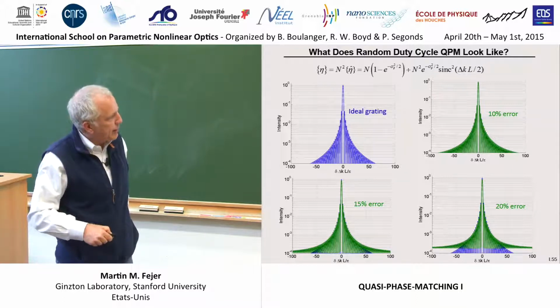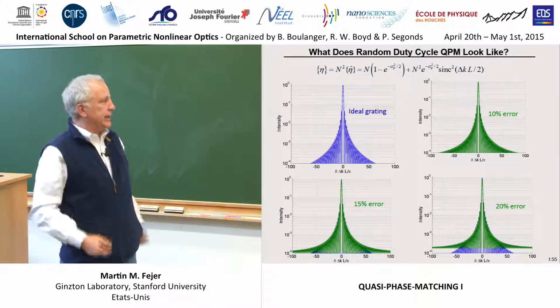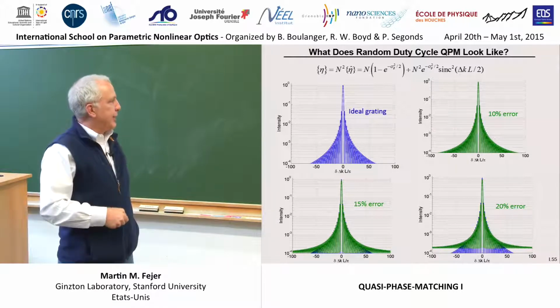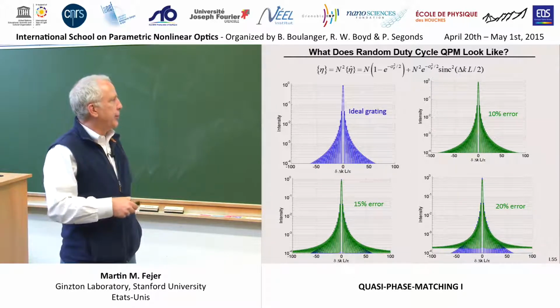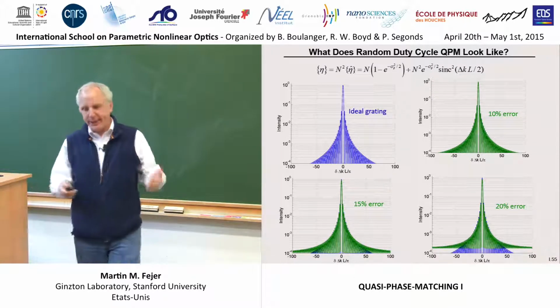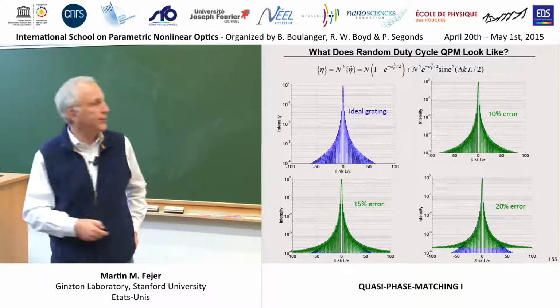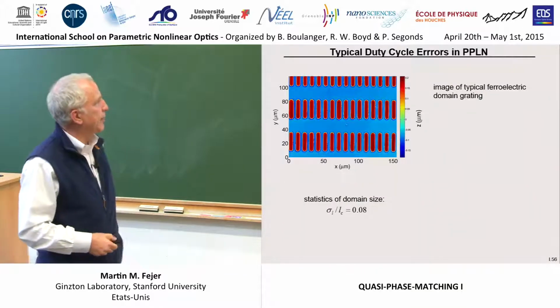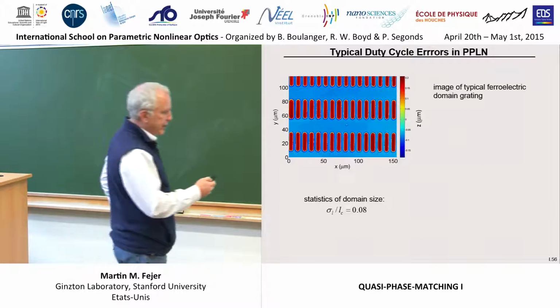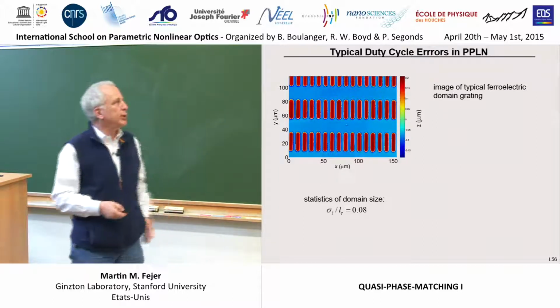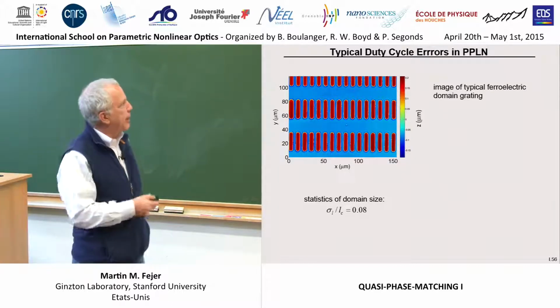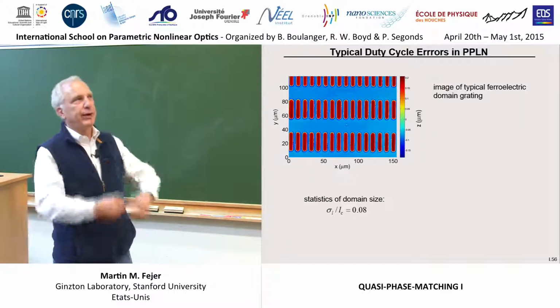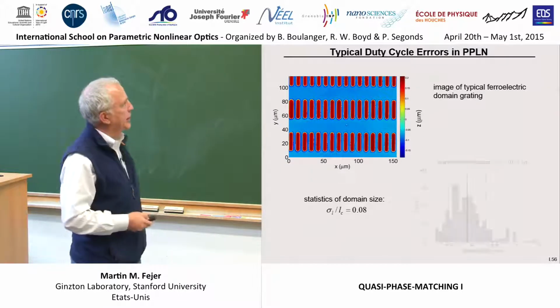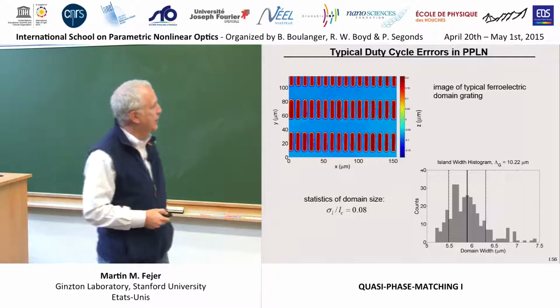And you can see this pedestal growing up at levels of 10 to the minus 3 or so of the peak, which usually you don't care about, but as I say, in situations where you're sensitive to those things, it can matter. This is just to give you a sense for how big these errors might be in a real grating. This is a Zygo interferometer image of an etched grating to determine its statistics, which we measured.